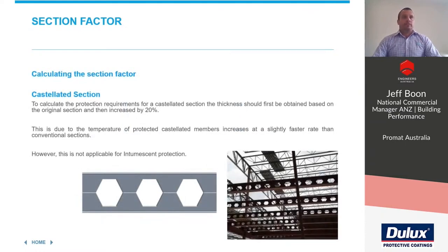Calculating castellated sections. To calculate the protection requirements for a castellated section, the thickness should first be obtained based on the original section and then increased by 20%. This is due to the temperature of the protected castellated members increasing at a slightly faster rate than conventional sections. This does not apply when looking at intumescent coatings though.